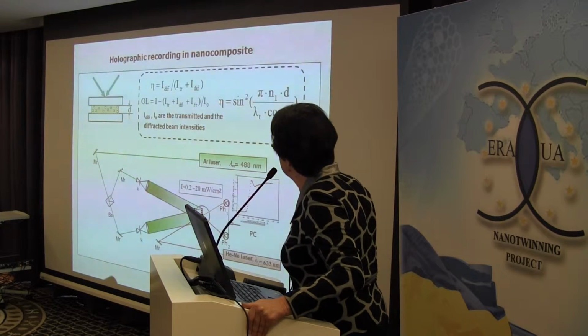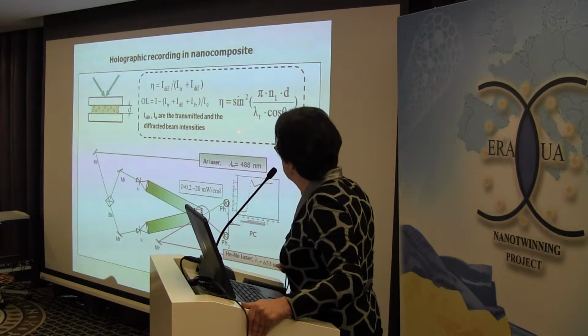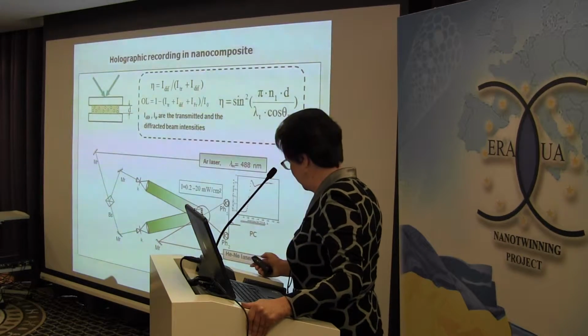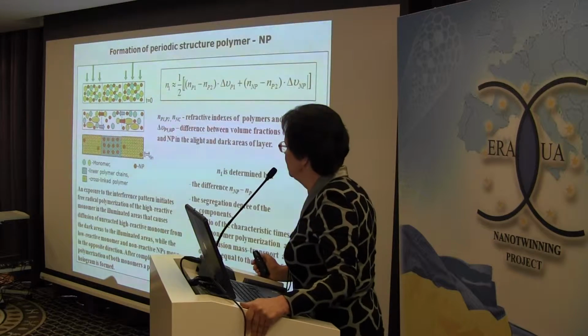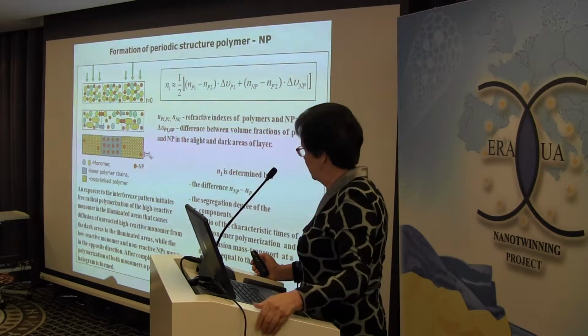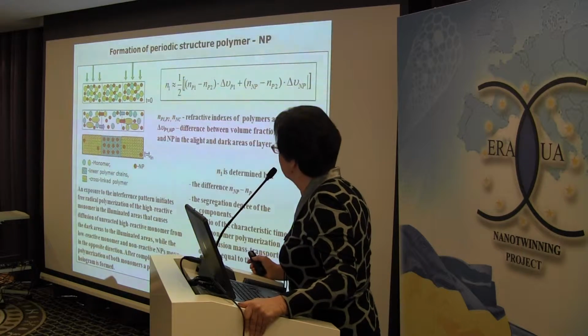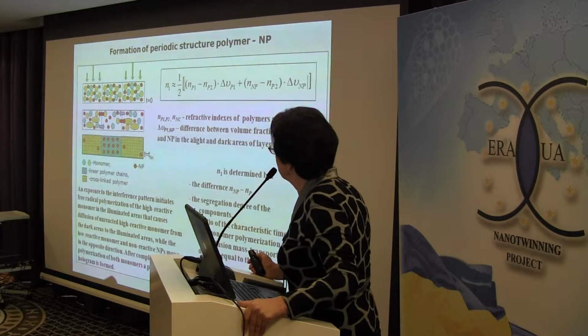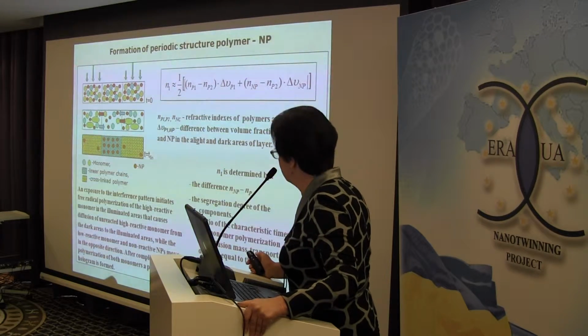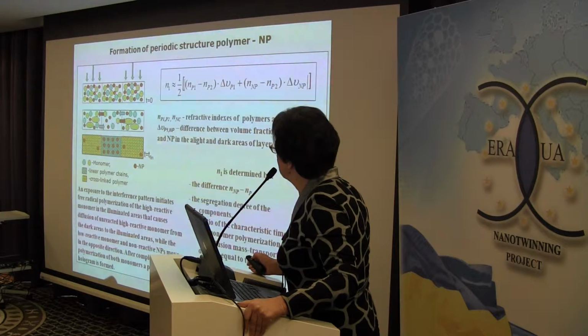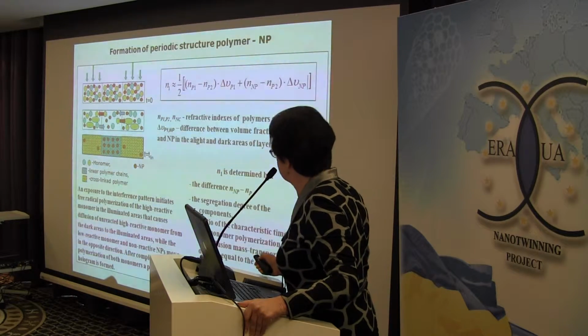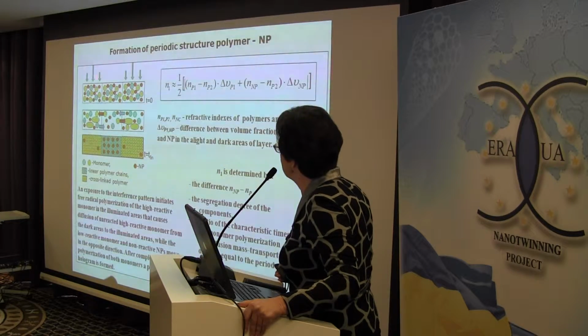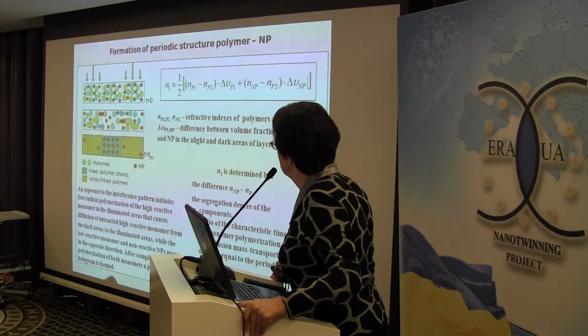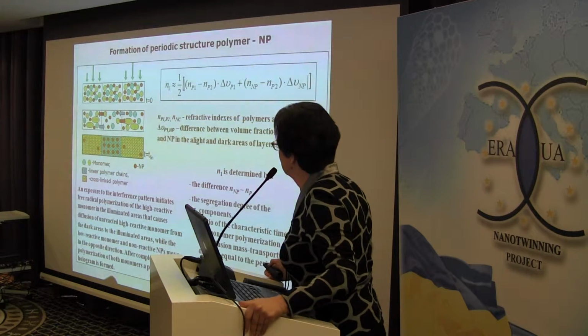The amplitude of refractive index modulation can be calculated from the well-known Kogelnik's formula. In the spatially periodic recording field, the recording field initiates the polymerization of the high reactive multifunctional monomer in the illuminated areas and causes the diffusion of this monomer from the dark areas to illuminated ones.